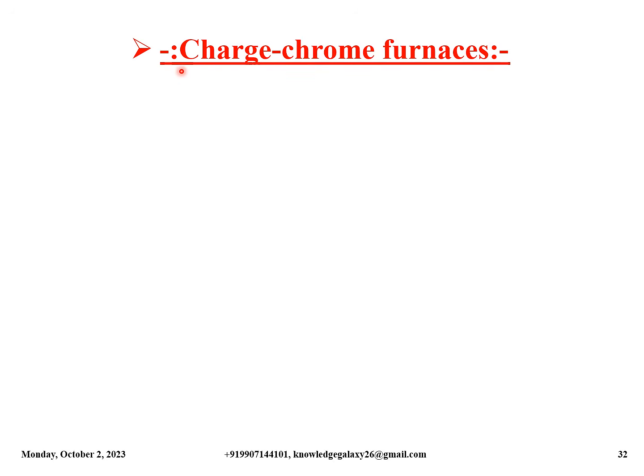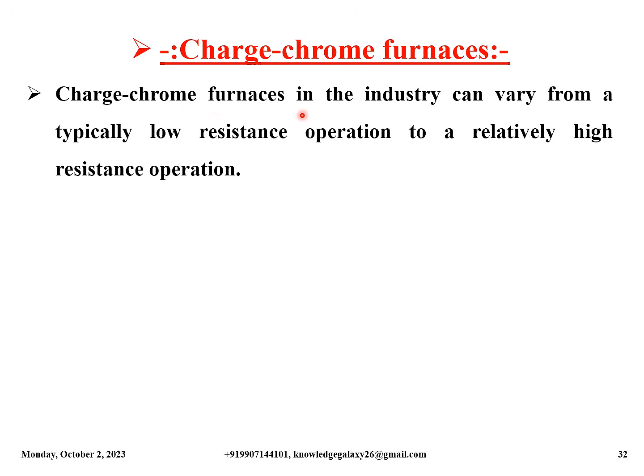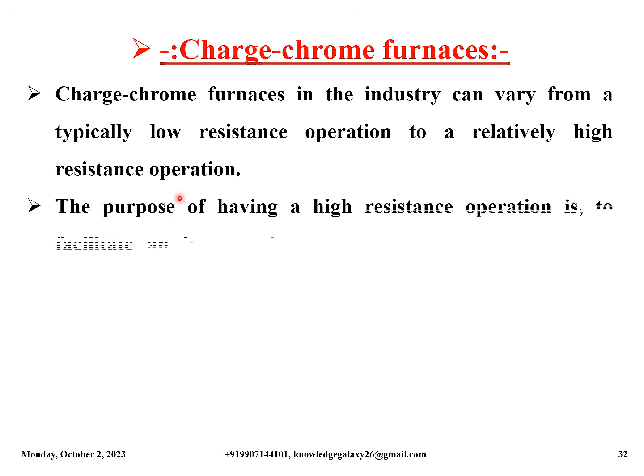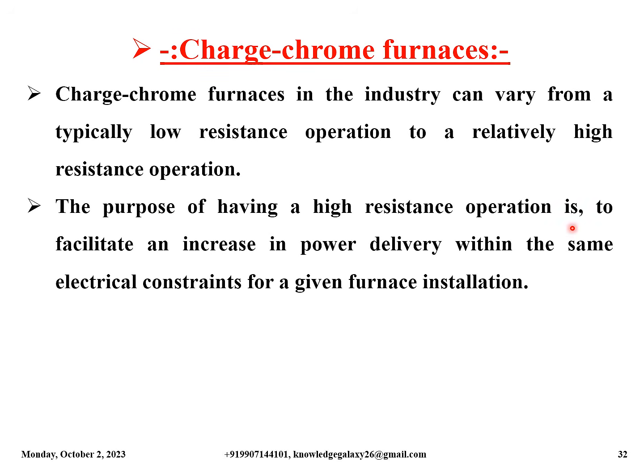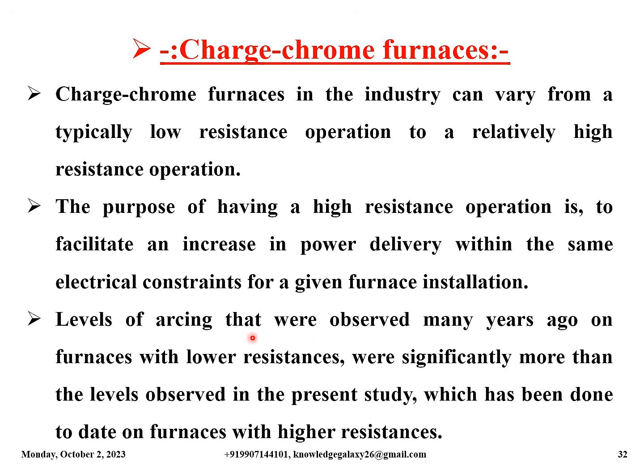Now let us discuss some points on charged chrome furnaces. Charged chrome furnaces in the industry can vary from a typically low resistance operation to a relatively high resistance operation. The purpose of having a high resistance operation is to facilitate an increase in power delivery within the same electrical constraints for a given furnace installation. Levels of arcing that were observed many years ago on furnaces with lower resistances were significantly more than the levels observed in the present study, which has been done to date on furnaces with higher resistances.